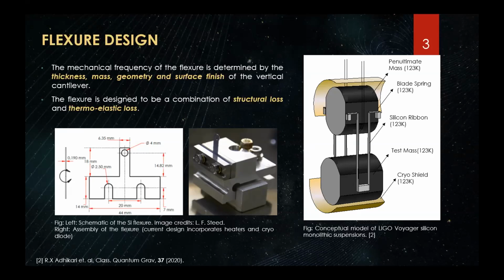And the flexure is designed to be a combination of structural loss and thermoelastic loss, where structural loss, or bulk loss, arises in the physical structure of your cantilever beam itself due to internal friction and other dissipative mechanisms. And your thermoelastic loss is due to localized heat flow from different stress and strain in your material, which results in deformation. And this thermoelastic loss depends on your geometry. And in our experiment, we care about the bending mode of the flexure.